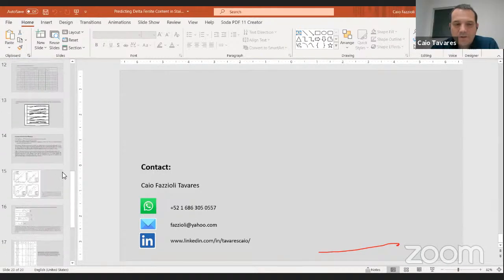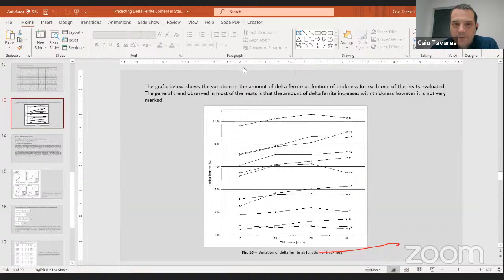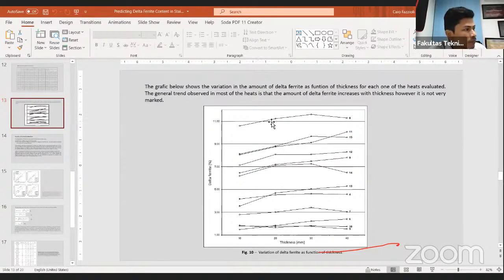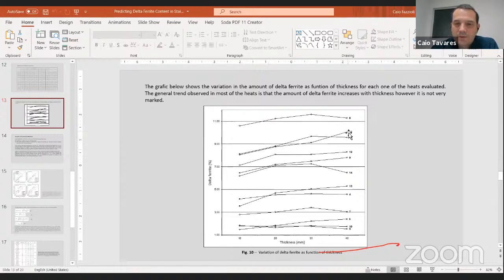In fact, we didn't observe a very pronounced effect of the thickness. I don't know if you can see my screen here. I'm checking this graphic. What we were expecting was a difference like that, increasing in thickness to get more delta ferrite. But in some situations it was almost flat, it didn't have much effect on the formation of the delta ferrite. It seems that it's a combination of the chemical composition and the geometry of the castings. Sometimes it's more pronounced, but sometimes it's not so pronounced. Okay.